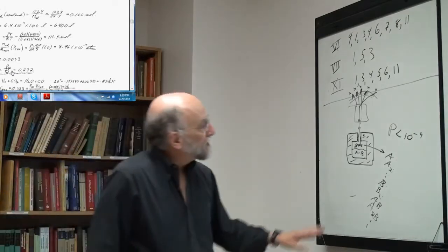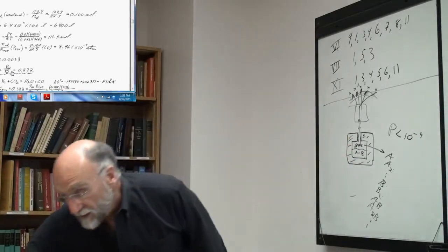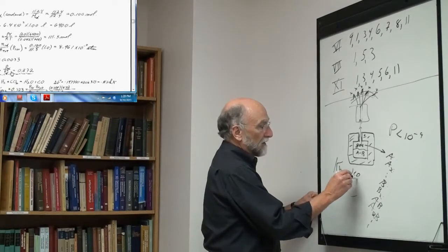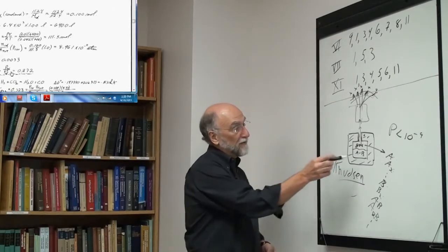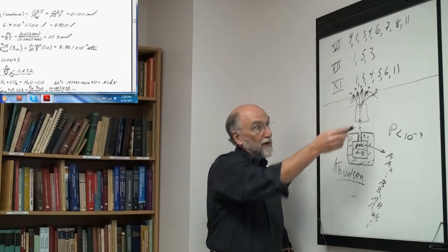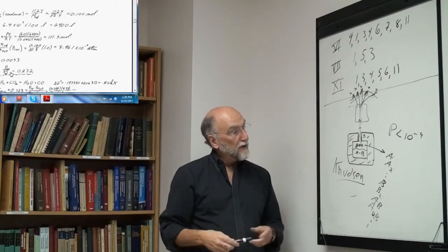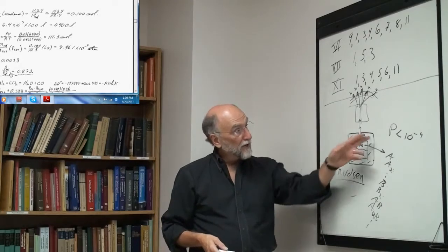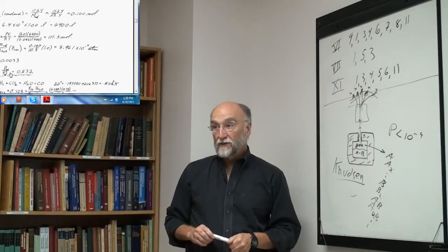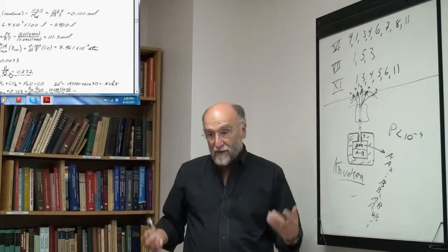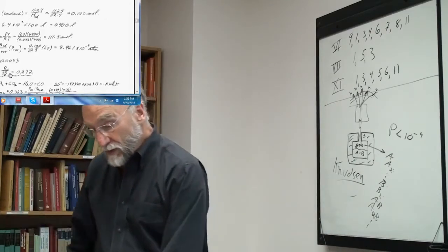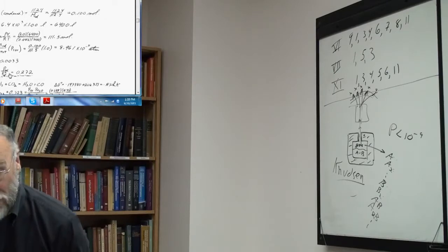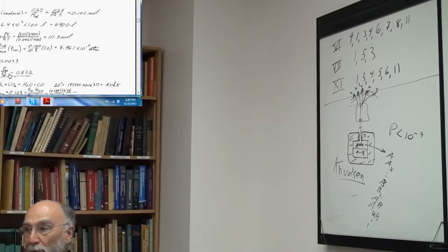Okay, so this is called a Knudsen cell. You have the Knudsen cell combined with a mass spectrometer, and it's a very powerful technique for analyzing the gas phase. But it only really works if you have quite low partial pressures. But this is really good for, say, metallic phases, liquid metals, tungsten, tantalum mixtures or something, where the partial pressure really is 10 to the minus 11 and so on.